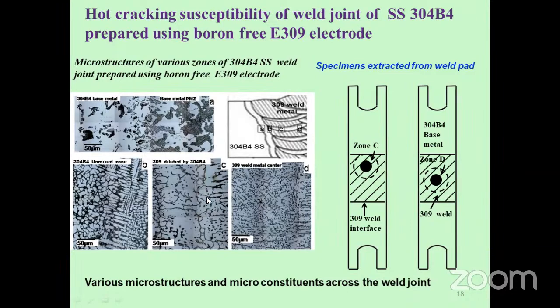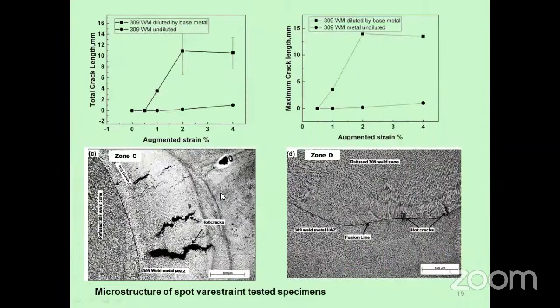to cracking. So to determine the cracking susceptibility of this region, we have made weld joints like this, and we have extracted hot crack specimens from the weld joints, and we have made spot Varestraint experiments in this region that is near to the weld interface where this base metal dilution is there. So we have again extracted the specimen from the weld joint, and we also tested the specimen at the weld center where there is negligible base metal dilution. So let us see the results from these experiments.